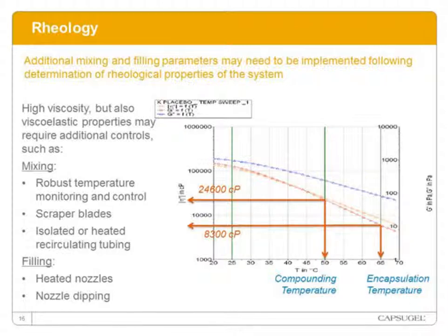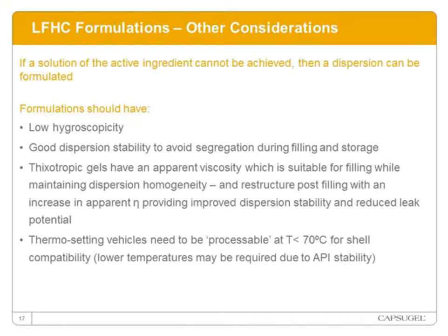Other mixing and filling parameters may need to be implemented following determination of rheological properties of the system. In this particular example, a high viscosity and viscoelastic system required additional controls, such as during the mixing step, robust temperature monitoring, scraper blades to ensure proper heat distribution, mixing, and homogeneity, and insulated or heated recirculating tubing to maintain an ideal temperature window. On the filling side of things, this process required heated nozzles as well as nozzle dipping to make sure we were able to fill the formulation from the bottom of the capsule all the way up and avoid potential spills.